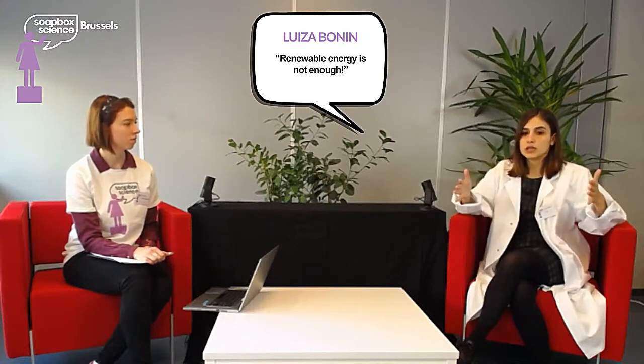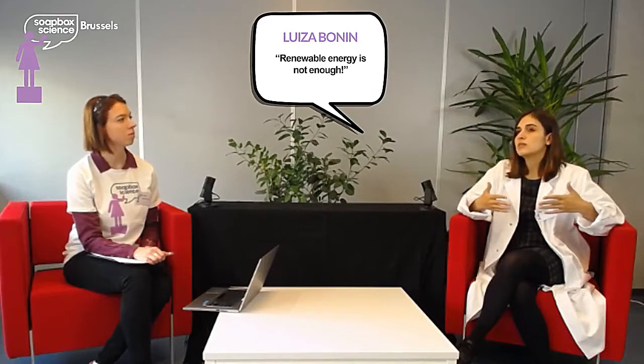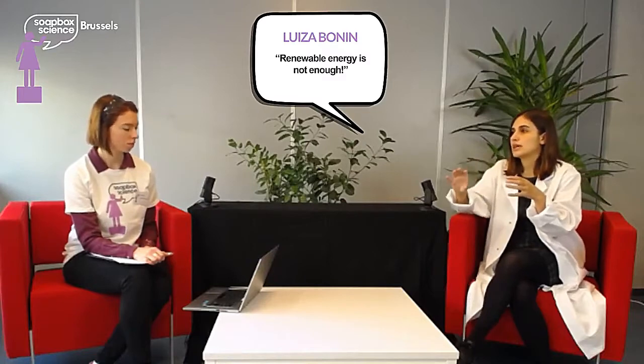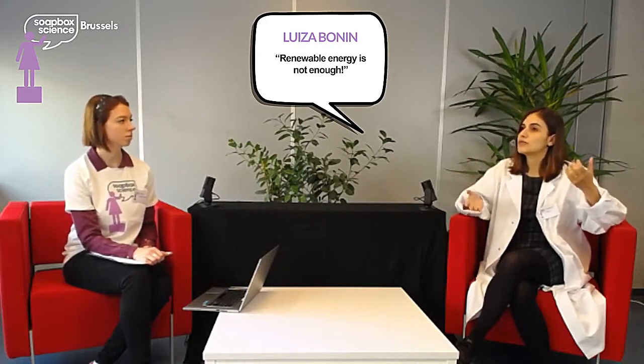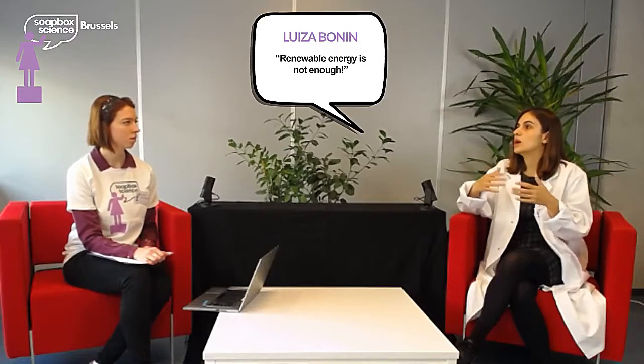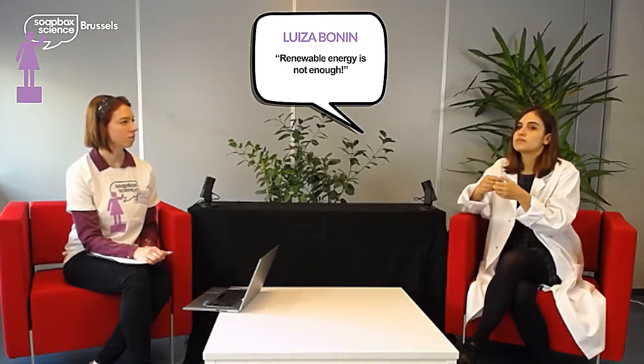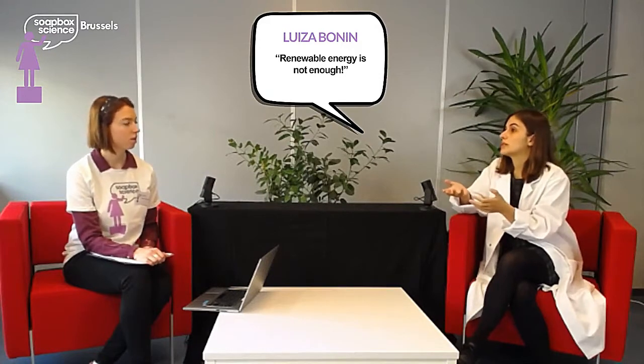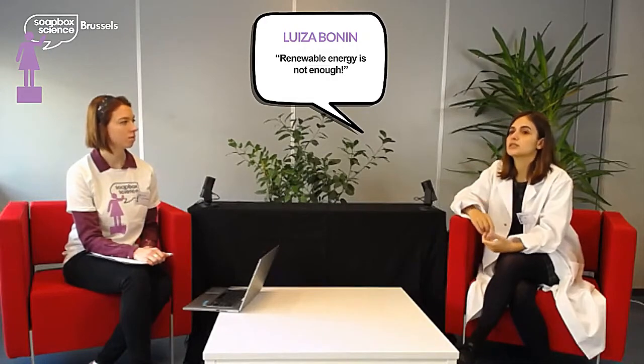It's a really interesting process because working with these electrochemical cells, we can recover also the other metals. The interesting part is that in the electrochemical cell, you always have what we call water splitting — that simply means taking the molecule of water and breaking it into a part that's acid and a part that's base, so H+ and hydroxides. With this change in pH, we can precipitate hydroxides — for example, we can precipitate magnesium as magnesium hydroxide and calcium as calcium hydroxide. So we don't have waste; we have byproducts. This is basically the process we have been optimizing here at the University of Ghent.